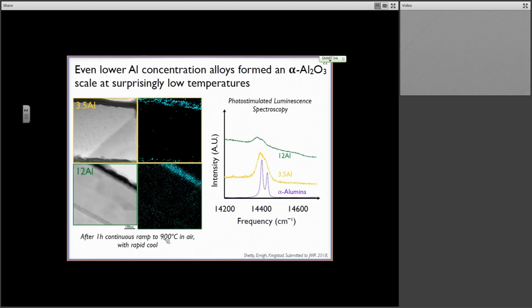All right, but the alpha alumina phase is actually the one that is protective. So when we go back and think about the application we started in, this is the one that we actually want to form, not any of the other ones. Okay, so we've demonstrated that this chemistry effect does in fact work. We were surprised by the formation of this continuous alpha alumina phase. But if you're paying close attention and you look at our micrographs on the left-hand side, the microstructure of the thin film looks a little bit different.